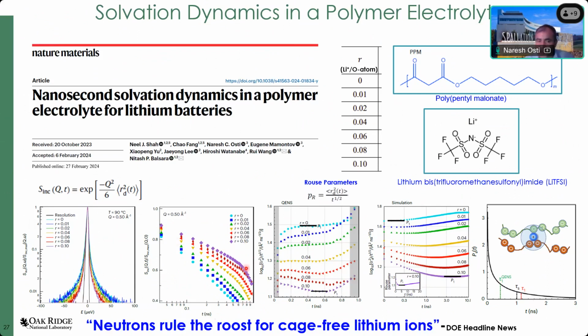Now we fit this data using this expression, from which you extract the mean square displacement of this particular system, and from which you can extract the Rouse parameter, which is given by this expression. It is nothing but the normalized mean square displacement with the square root of the time, and we are plotting this as a function of the temperature. What you can see here is that at low salt concentration, up to 0.02 concentration, it shows some sort of the natural type of Rouse parameter.